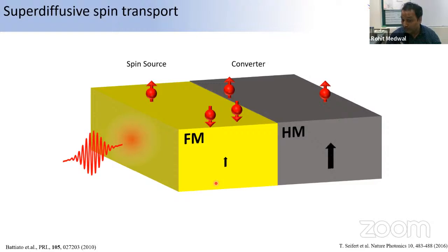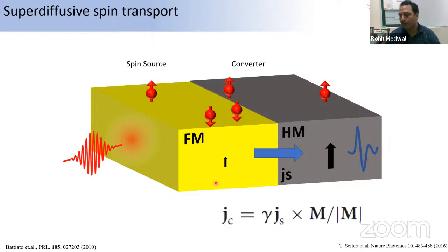There is induced magnetization in the heavy metal because the spin has been pumped into the heavy metal, which sets up a spin current in the heavy metal. And this transient spin current, which is 100 to 300 femtoseconds, as I just explained, because of the magnetization, gives rise to a terahertz photon. Because, as we know, any radiating charge gives rise to radiation. So this terahertz photon generally lies in the picosecond time scale, and it arises mainly because of the transient charge current, which is generated by the J_C. And this J_C can be controlled by spin-to-charge conversion.